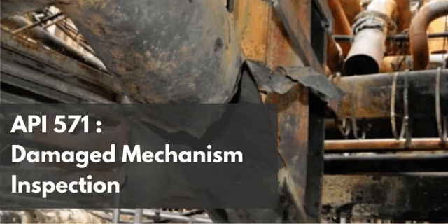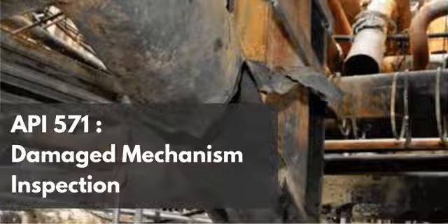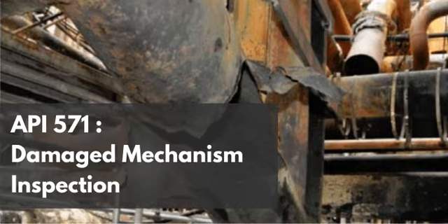This changing magnetic field induces secondary electrical currents, eddy currents, to flow within the surface layer of the carbon steel. And because of the skin effect in alternating currents, these eddy currents are highly concentrated right at the surface. Exactly where Amine SCC initiates. Right. So in sound metal, these eddy currents flow in uniform, predictable, circular patterns. But a crack acts as a high-resistance barrier. So when the eddy currents encounter the crack, they're forced to flow down and around the root of the crack. Yeah, and this physical detour changes the path length of the current, which in turn alters the secondary magnetic field produced by the eddy currents themselves.